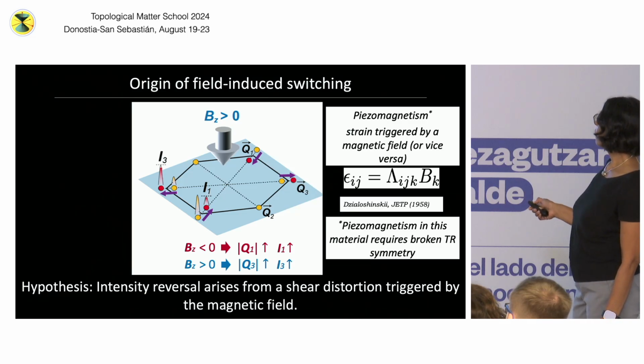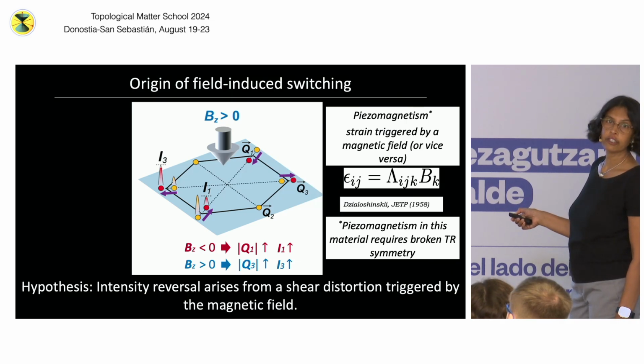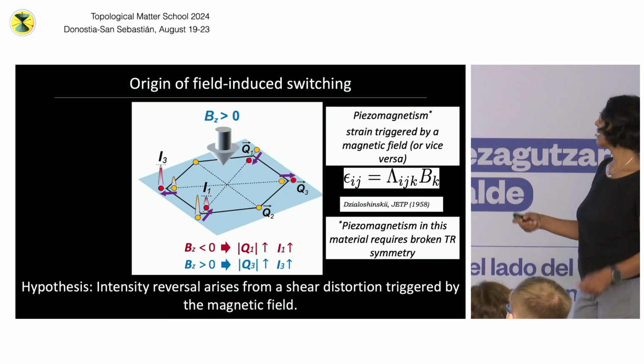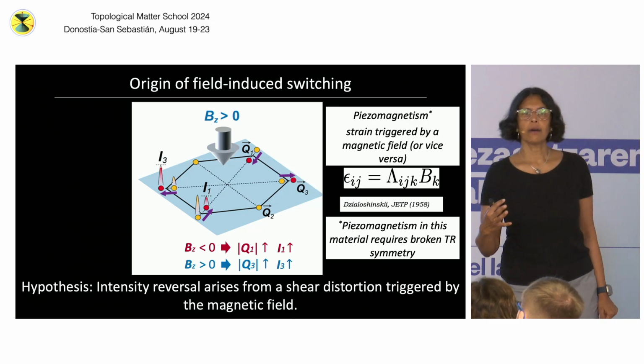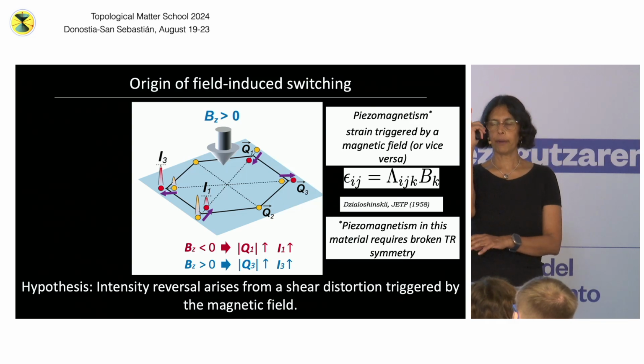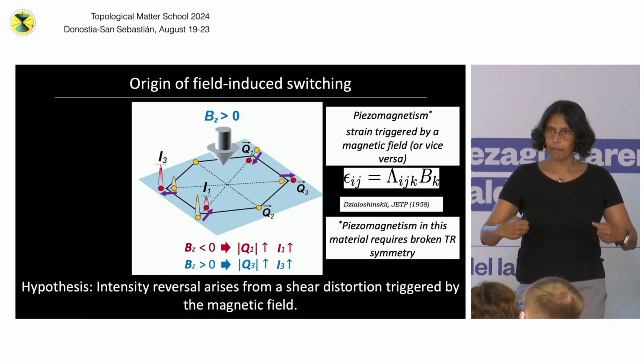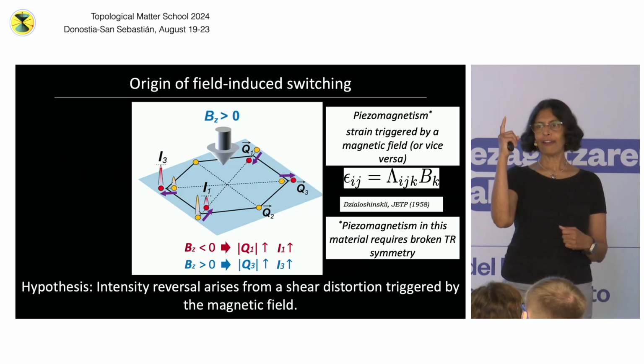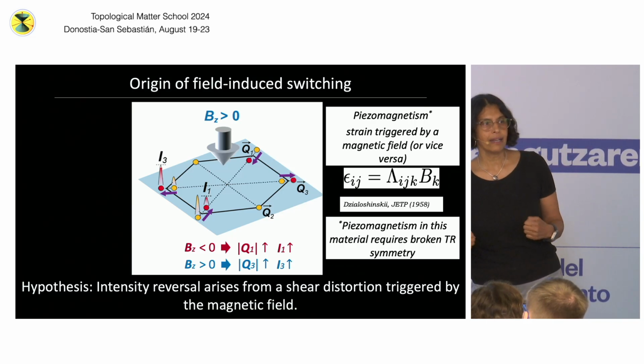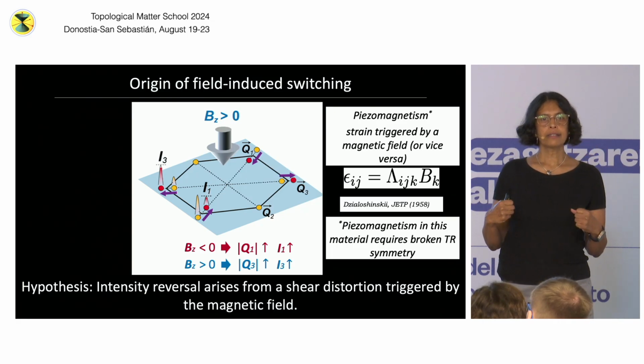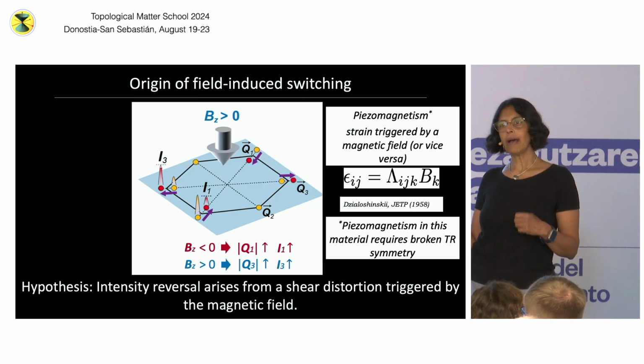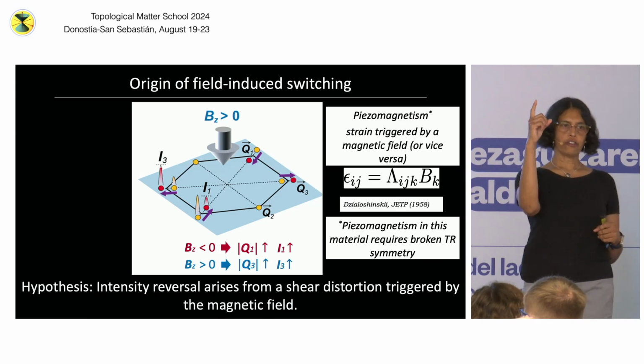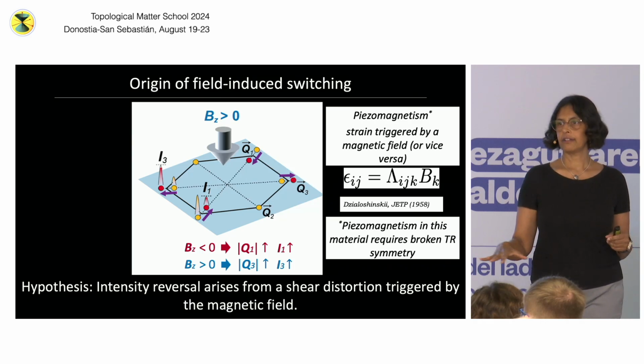So what we expect is that when you apply a perpendicular field, if the intensity goes up, then the lattice Fourier transform peaks should also shift correspondingly. That means the lattice has contracted. It's very difficult to see how a perpendicular field could move things in the XY plane, right? How can you apply a field in the Z direction and have motion in the XY plane? One way to do this is by a mechanism called piezomagnetism. Piezomagnetism is exactly this. You apply a field in one direction, and you have a response in the perpendicular direction.